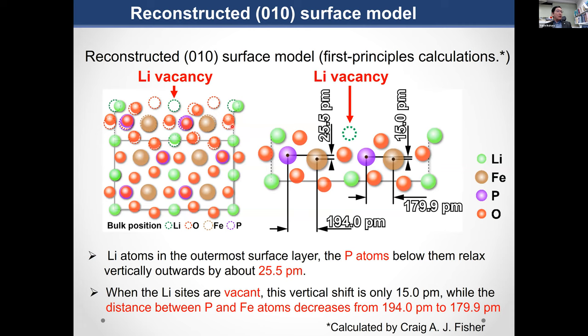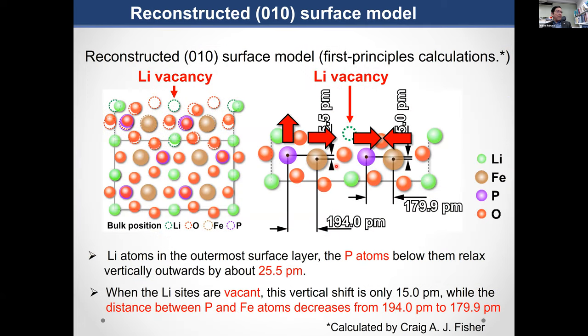I don't have time, so I'm not going to explain in detail, but the surface is actually relaxed because if it is rich in vacancy, the phosphorus is shifted to this direction. So this shift and this relaxation is consistent with this result. I'm not going to explain this detail.